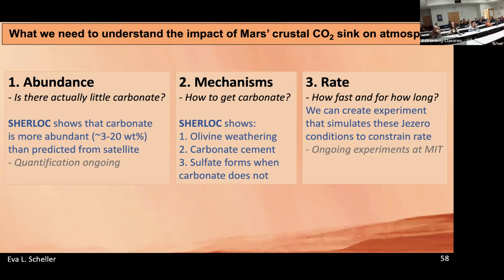Well, one thing that we got from our observations is an actual abundance of carbonate. So we observed that there is 3 to 20 weight percent carbonate in our rocks. We see 3 to 10 weight percent in the igneous olivine cumulate, and we see upwards of 20 weight percent in this fluvial sandstone with water derived from an olivine rock watershed. And this was actually found in areas where we didn't observe any carbonate absorptions from orbital data. Taken at face value, that actually means that depending on the outcrop exposure and conditions, you may not observe a lot of carbonate with this satellite. So there's a constraint there on the detection limits of this satellite.